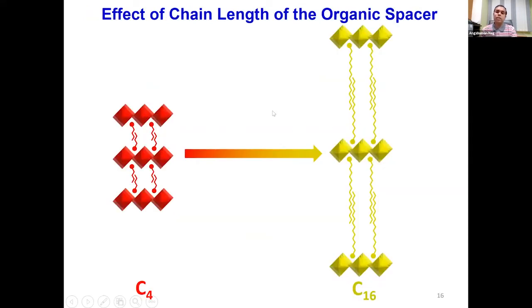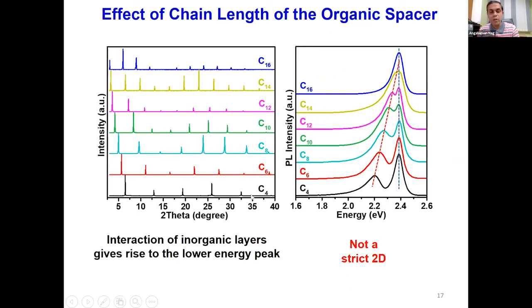However, this interaction hypothesis that we have, we can also verify by changing the chain length of the organic layer. So this is the C4 system, with a 4 carbon chain, and we can vary the carbon chain length from C4, C6, up to C16. When we do so, we see that expectedly, when we increase the chain length of the carbon chain, the interlayer distance increases, and that's what is reflected in the XRD data. Now, interestingly, for all these samples, the high energy emission remains rock steady, it doesn't change.